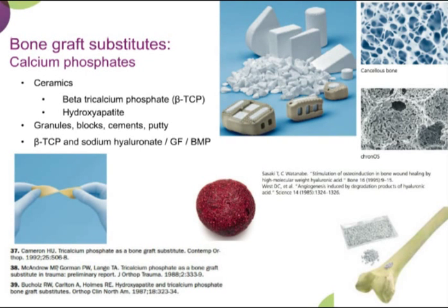It's created by a process called sintering, where non-metallic mineral salts are heated to temperatures above 1,000 degrees, and they form highly crystalline structures. Here's a picture of Chronos graft, for example. There's controversy about the different types of beta TCP in terms of pore size. There are micro and macro pores: micro pores we consider very small ones, and these larger ones are macro pores.